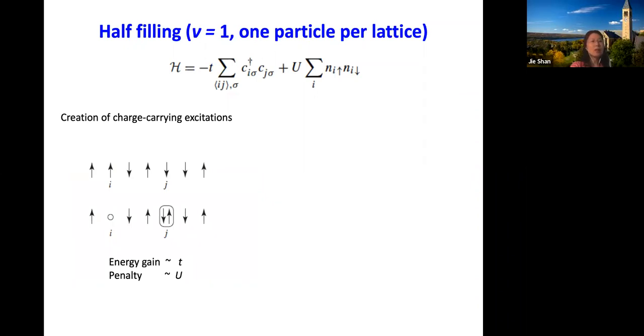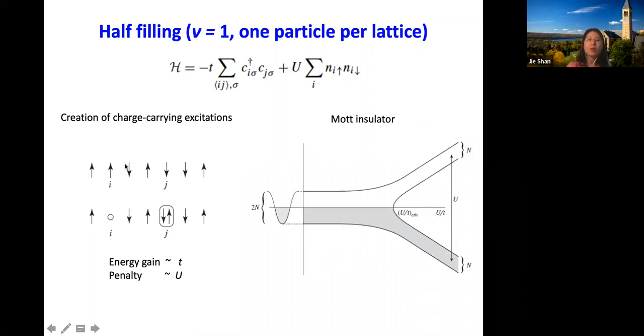As I said, it's a difficult problem to solve. We have a pretty good understanding of what's going on in a few limiting cases. One of them is half filling, when the band is half filled. That's the case when we have one particle per lattice site. So in this case, in order to create a charge-carrying excitation, in the absence of interaction, this is a metal because the band in the single-particle picture is a half-filled band. So we all know that.